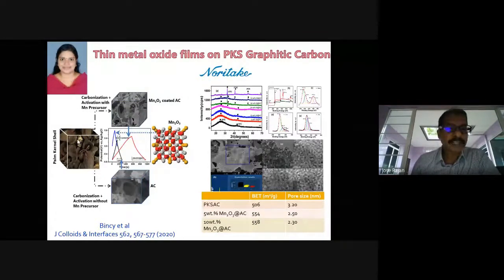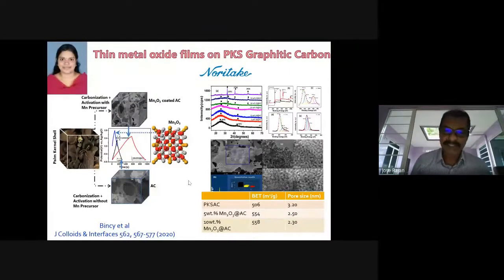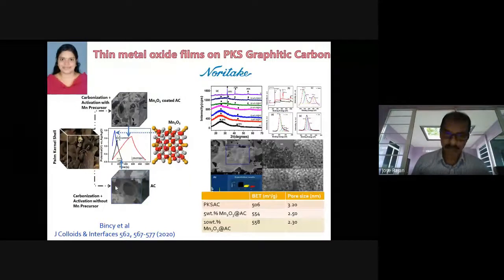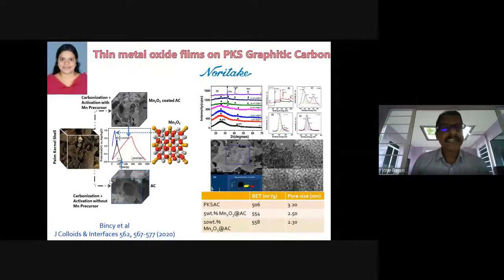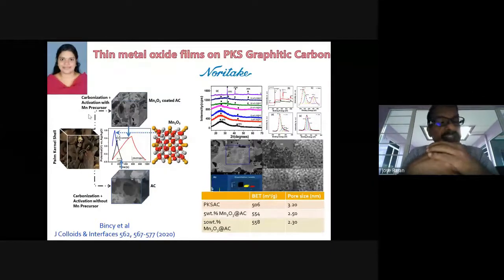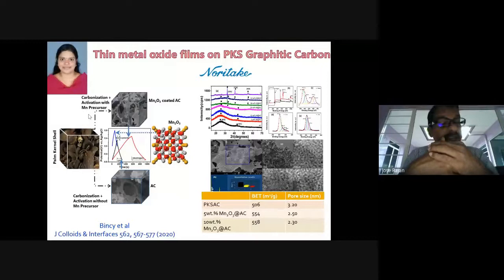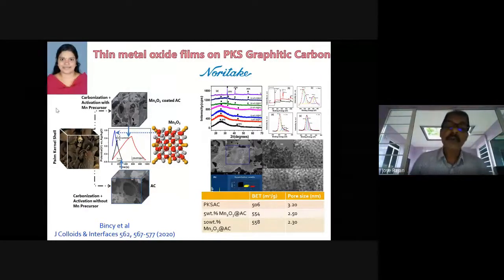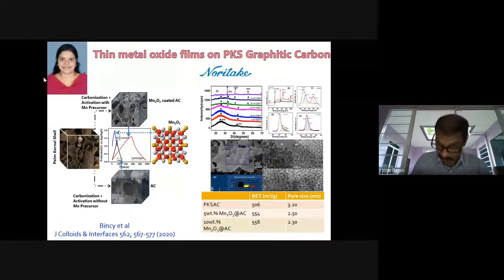This one is the palm kernel shell, and if we conventionally heat it, we get porous carbon, like what I showed at the bottom. And if we make a special processing with a small amount, about 10 weight percentage, of metal oxide, in this case we used manganese oxide. Manganese oxide is also highly abundant on the planet and is very cheap. So when we overcoat this metal oxide, manganese oxide,